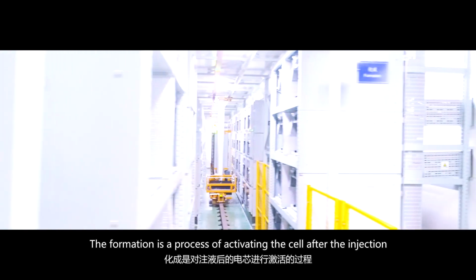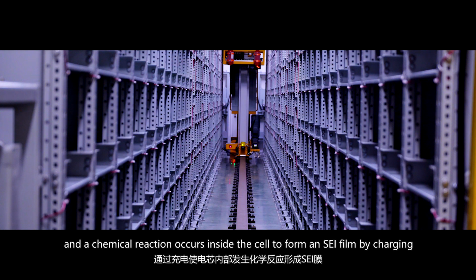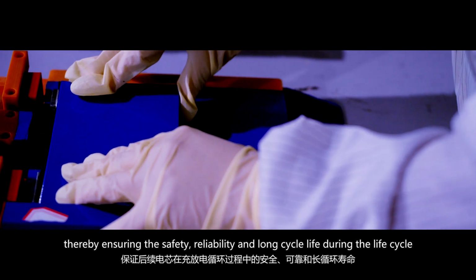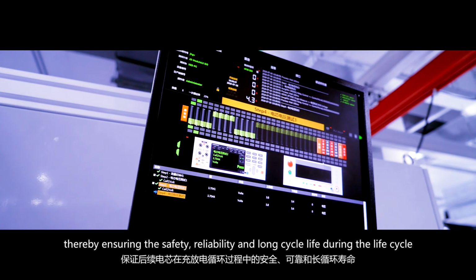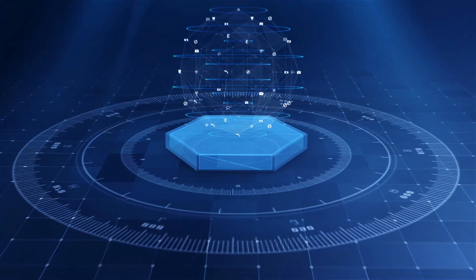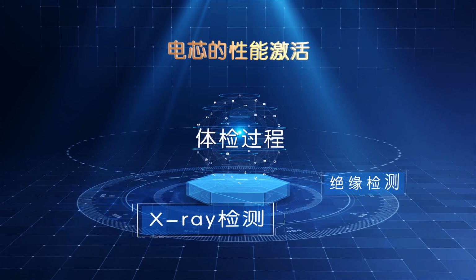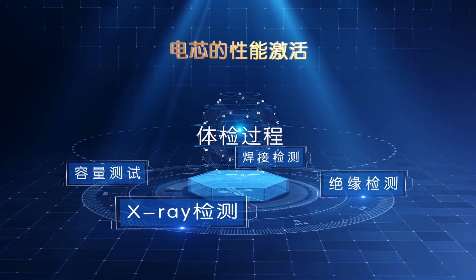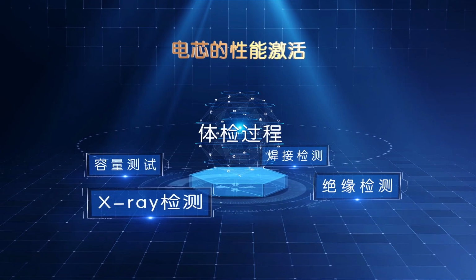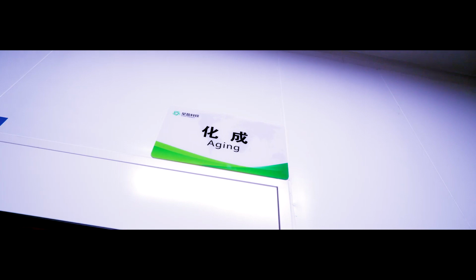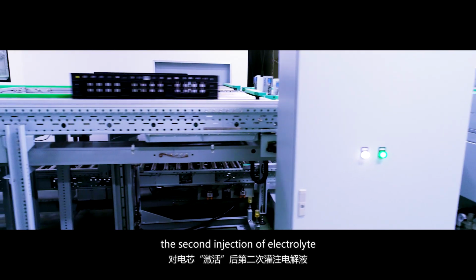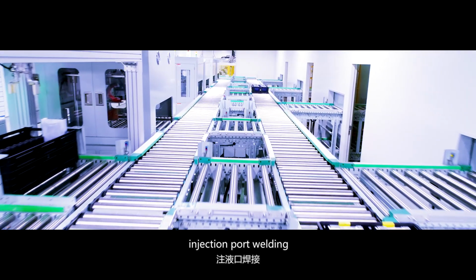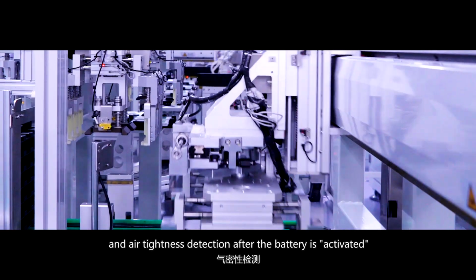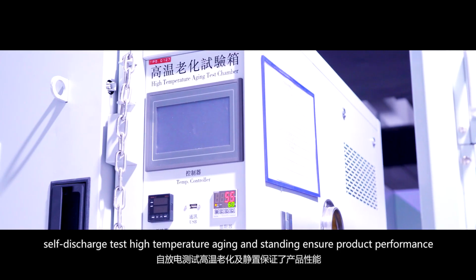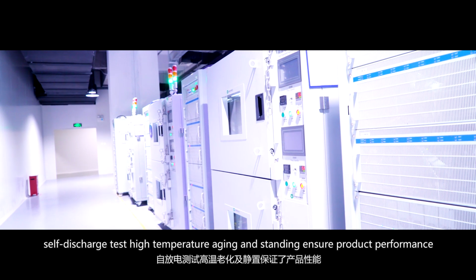The formation is a process of activating the cell after the injection, and a chemical reaction occurs inside the cell to form an SEI film by charging, thereby ensuring the safety, reliability, and long cycle life during the life cycle. The performance of the battery cell is activated, and it also undergoes a series of physical inspection processes such as X-ray inspection, insulation inspection, welding inspection, and capacity testing. The formation process also includes the second injection of electrolyte, weighing, injection port welding, and air tightness detection after the battery is activated. Self-discharge testing, high-temperature aging and standing ensure product performance.